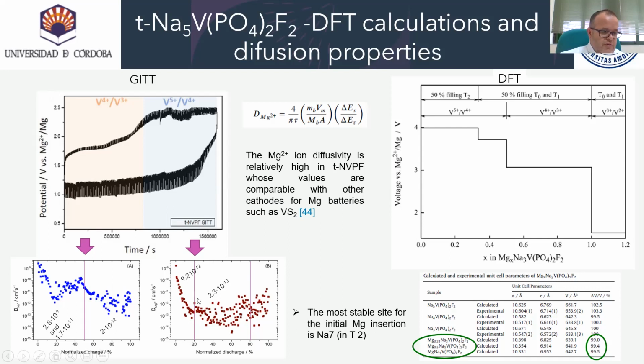During the discharge, magnesium ion insertion in tunnel T2 adopts an average value of 2.2 times 10 to minus 13 square centimeter per second from 20 to 80% of the normalized capacity. But the diffusion coefficient at high potential is somewhat higher. These results indicate that magnesium ion diffusivity is relatively high, whose values are comparable with other cathodes such as vanadium disulfide.